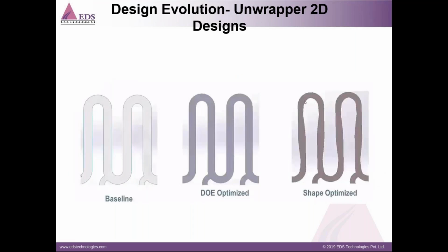I have shown you these results in 3D, and I also wanted to show you in 2D, since it's a little better to see how the geometry changes. We start with this baseline geometry of the stent component, and the parametric optimization model is in the middle. It has undergone a design of experiment study and optimization, for which you can see the length is slightly longer and the radius is slightly smaller. Once we do the shape optimization, the shape has changed quite a bit. The radial shape is slightly deformed and pushed inwards, and the long straight lines are more contoured in those regions. Since we applied cyclic symmetry, you can see that the two U-shaped structures are very similar.